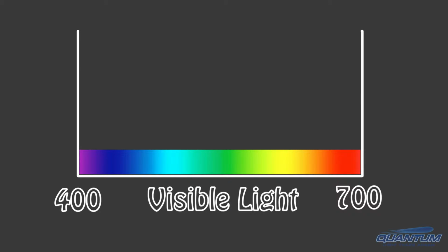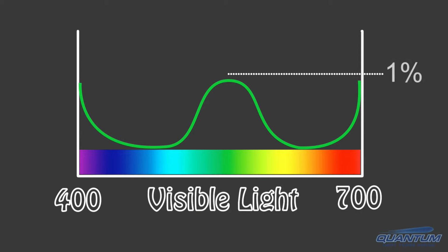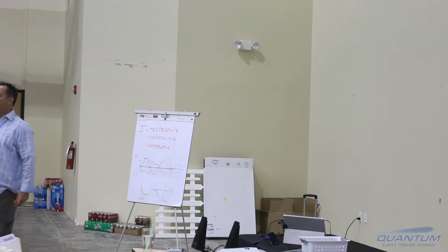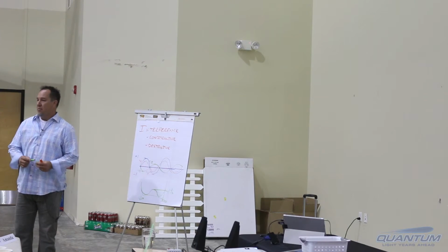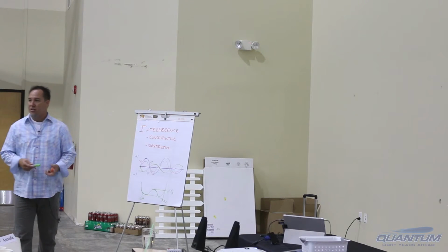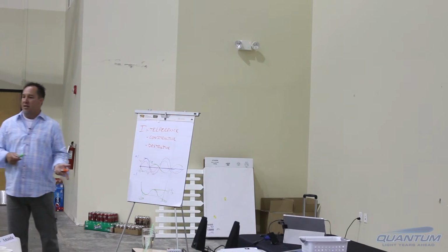What does a green AR coating look like? Looks like that, right? So this is usually around 1%. So where's that 1% going? That's 1% per side. So you lost 2% of the total amount of green light that you could possibly see. I just took it away from you. Because I'm reflecting it, you don't get it. So the wearer is actually losing 2% of the green light.